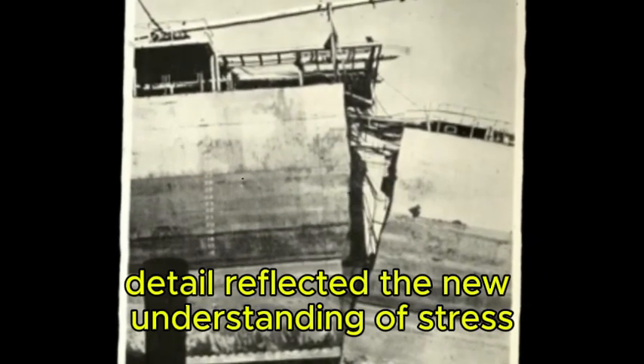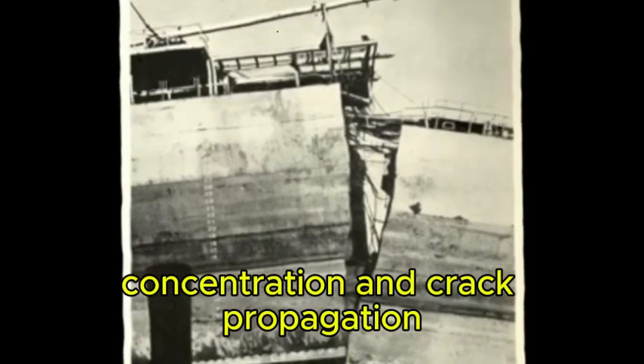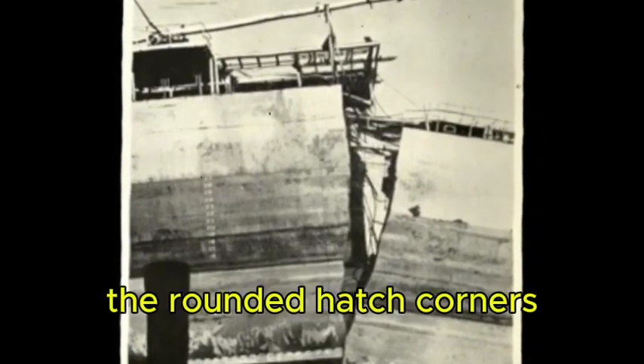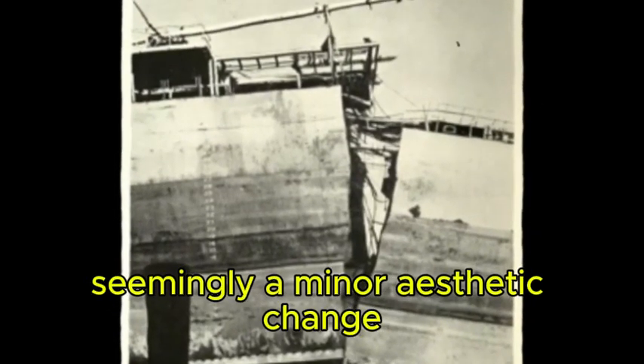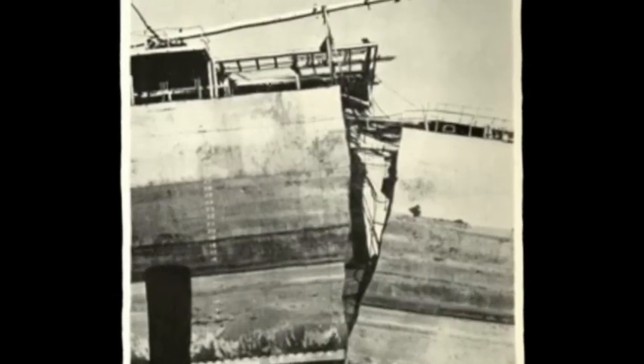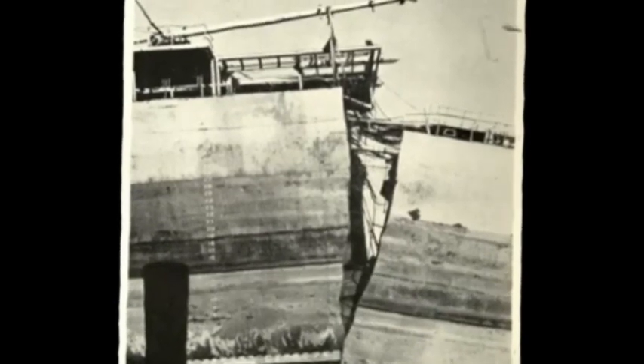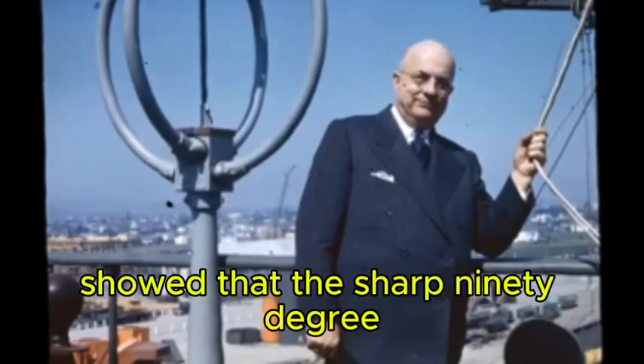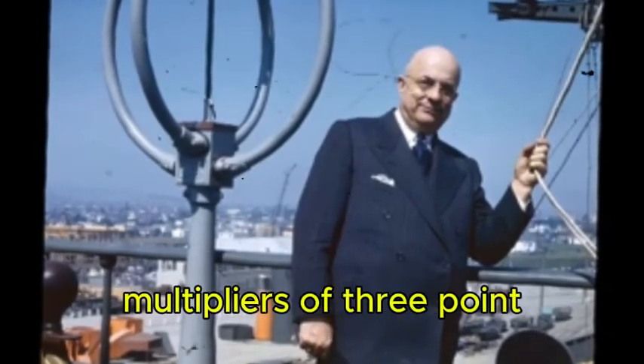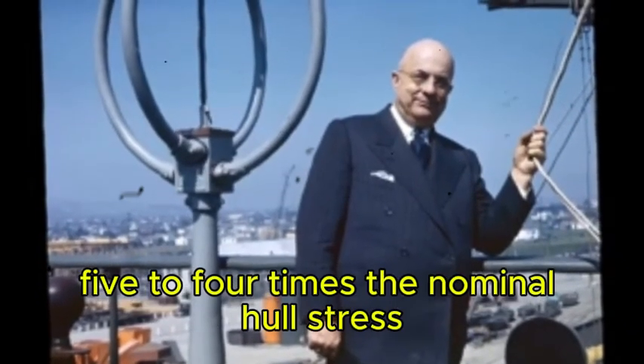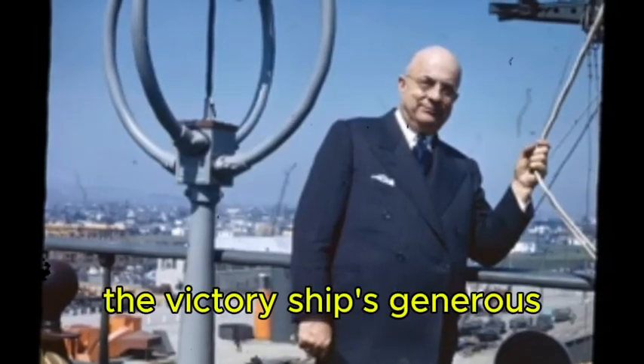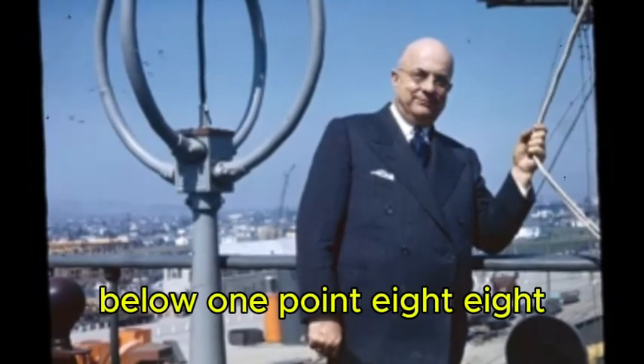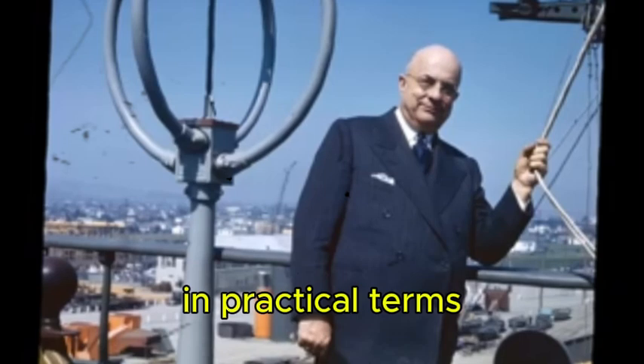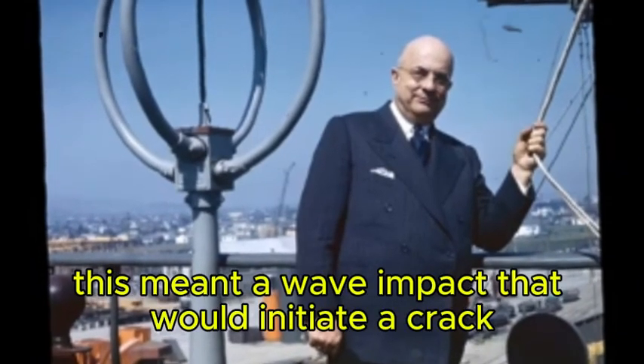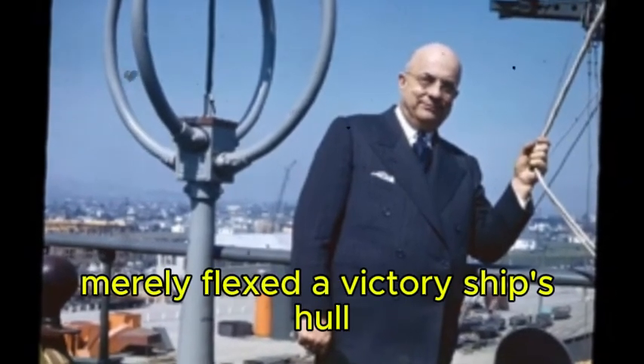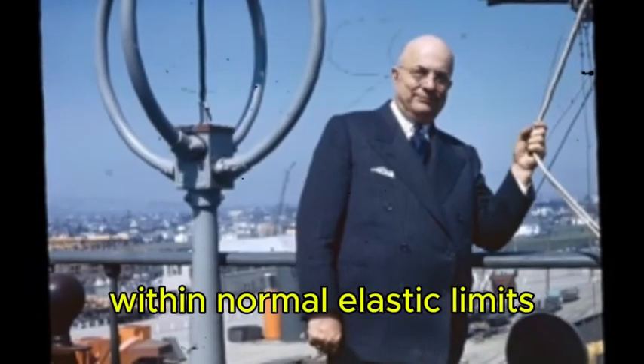Every structural detail reflected the new understanding of stress concentration and crack propagation. The rounded hatch corners, seemingly a minor aesthetic change, reduced local stress concentrations by over 60%. Engineering calculations showed that the sharp 90-degree corners in Liberty ships created stress multipliers of 3.5 to 4 times the nominal hull stress. The Victory ship's generous radii kept stress multipliers below 1.8. In practical terms, this meant a wave impact that would initiate a crack in a Liberty ship merely flexed a Victory ship's hull within normal elastic limits.